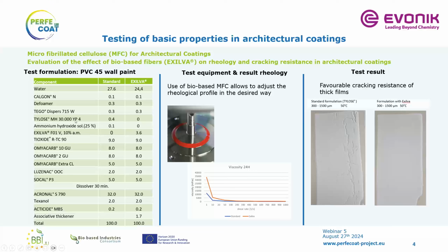And we tested it against the standard, which is a cellulosic thickener, Tylose. And you can see maybe the use level seems a bit hard, but the Exilva is a slurry, which is 10% active in water. And it's very easy to use and very compatible to use in formulation. And at the bottom of the table, you can see the let down with the binder, a styrene acrylic emulsion, classical for wall paint.